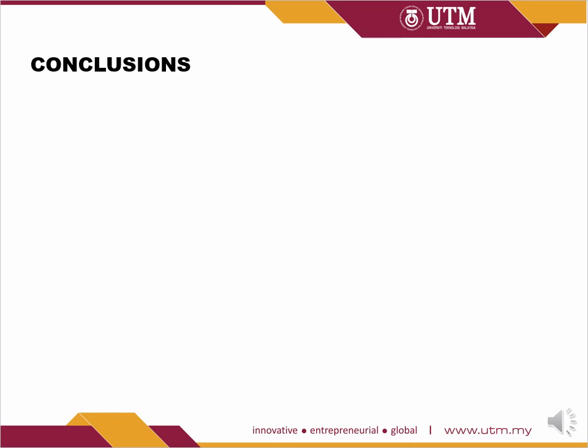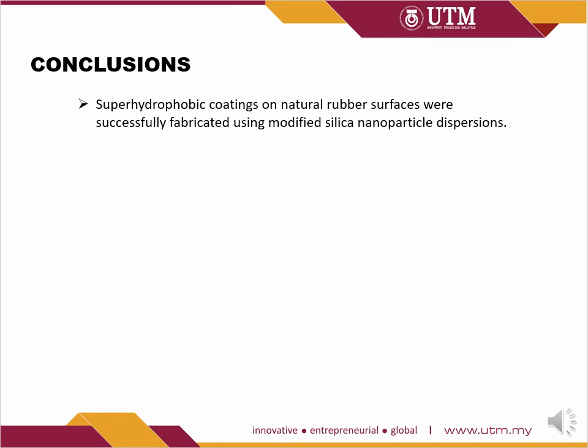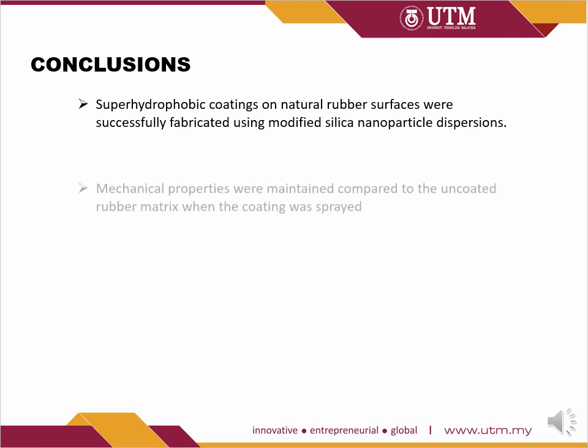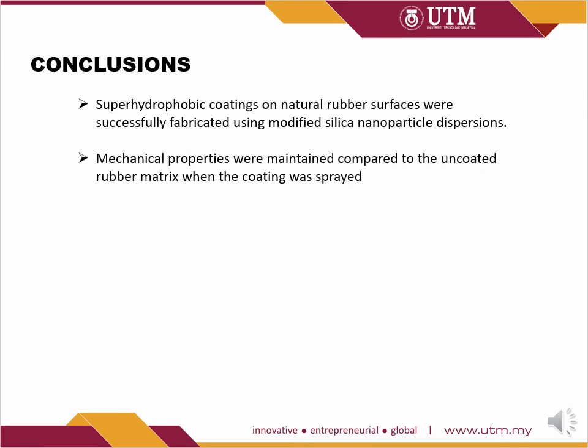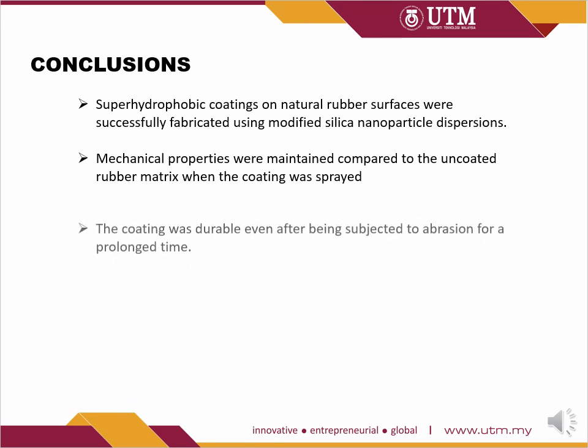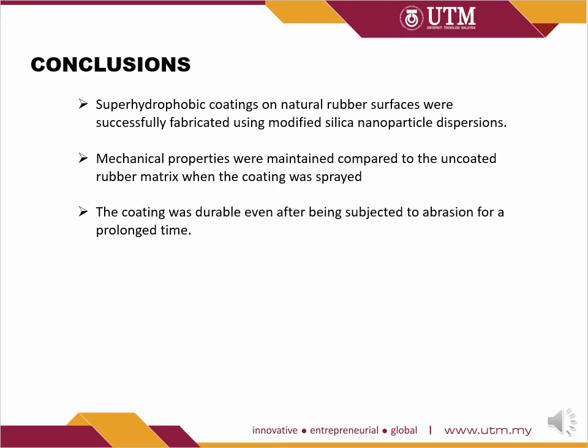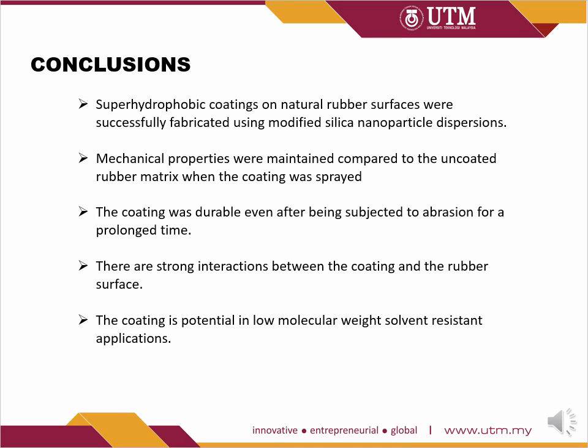In conclusion, superhydrophobic coatings on natural rubber surface were successfully fabricated using modified silica nanoparticle dispersion. In addition, the mechanical properties were maintained compared to the uncoated rubber matrix when the coating was sprayed. Next, the coating was durable even after being subjected to abrasion for a prolonged time. This observation, together with the FTIR characterization evidence, suggests that there are strong interactions between the coating and the rubber surface. Lastly, the coating was significantly resistant towards methanol, suggesting its potential in low molecular weight solvent-resistant applications.